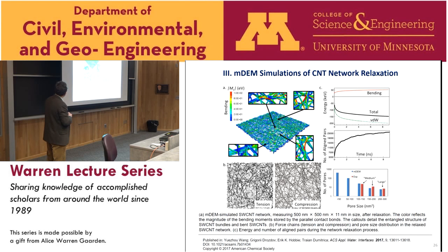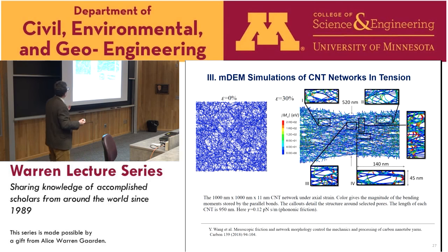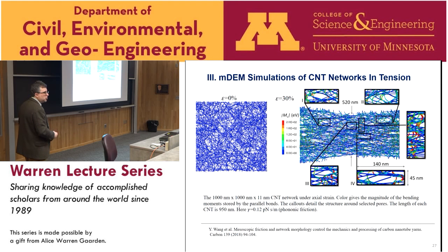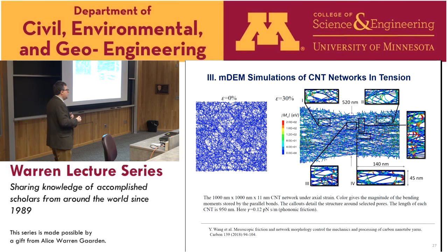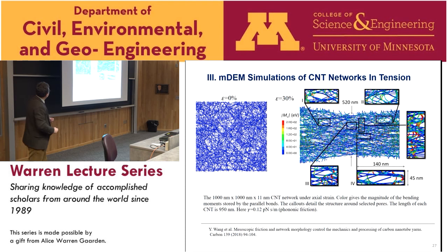This method of creating the mat resembles experimental observations. We are now in good shape to probe the stretching of these structures. You see how the structure looks when you stretch it — this is the mat at zero strain. We grip some elements on the left and right and apply deformation in a velocity-controlled way. The structure responds by extension on a large scale, with some decrease in width as a function of time. The individual tubes respond to the applied strain by relaxing, by zipping — essentially aligning.